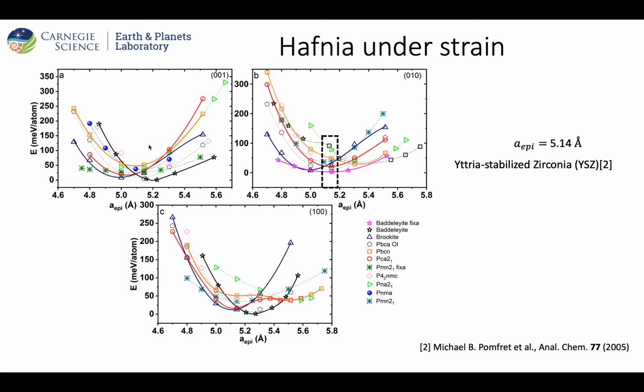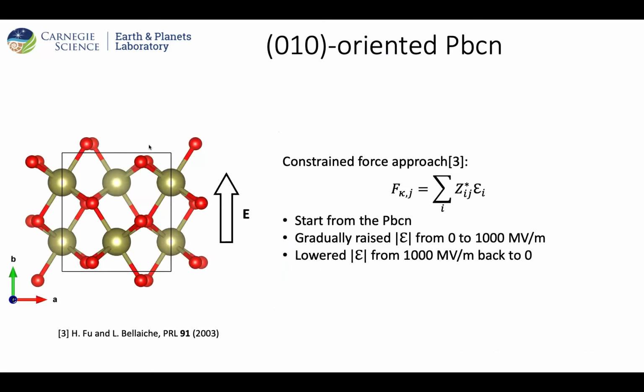Here we'd like to focus on the 010 oriented film, starting with the Pbcn, at an epitaxial lattice constant which is 5.14 angstrom. This is approximately the lattice constant of yttrium stabilized zirconia. And toward the end, I'm going to tell you the reason why we chose the Pbcn. But let's just say we start from the 010 oriented Pbcn, apply strain in plane and the electric field out of plane. We apply the electric field through constraining the forces on the atoms. Starting with the Pbcn, we gradually increase the electric field from 0 going to 1000 megavolt per meter, and then coming back down all the way to 0 again.